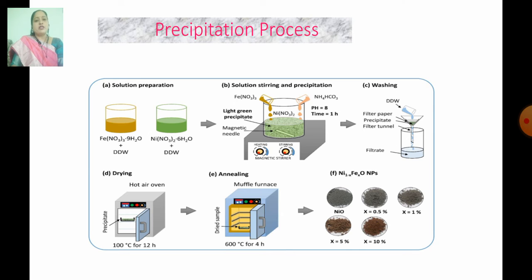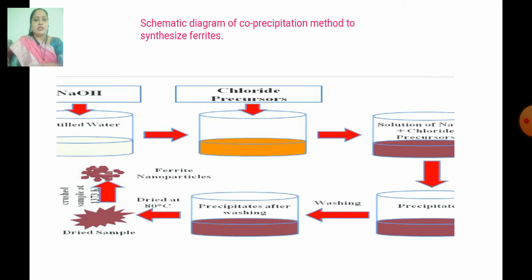So here there is a precipitation process in which, in this figure, it is shown that there is a solution which I have prepared firstly, that is ferric nitrate, and there is nickel nitrate, and these two combined are further heated, and after that we filter it, and after filtering, for drying we keep it in a furnace, and then for annealing it is again heated at about 600 degrees Celsius for 4 hours, and then we will get the powder, and that powder is crushed, and in this way this is the complete precipitation process. This is a schematic diagram of the co-precipitation method to synthesize ferrites, which is shown here.